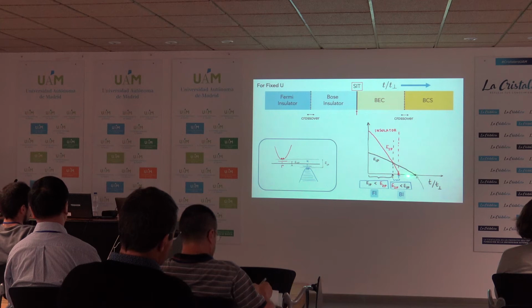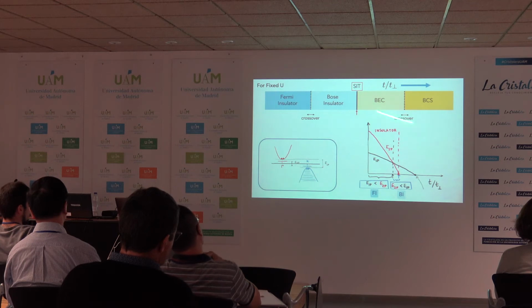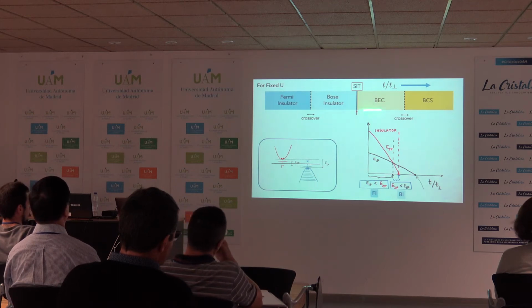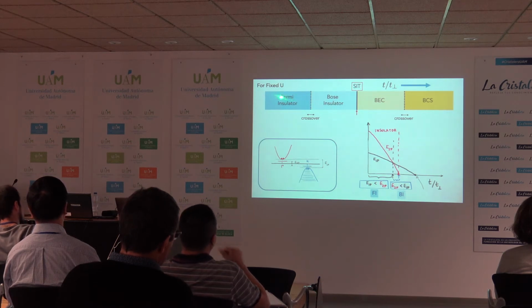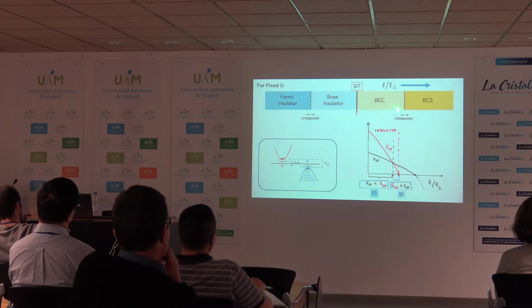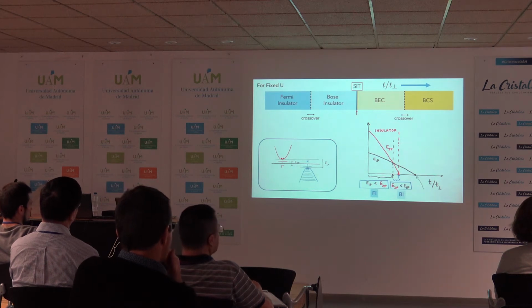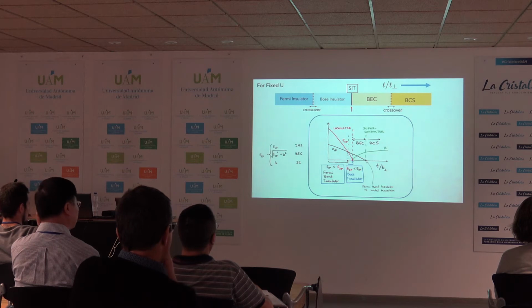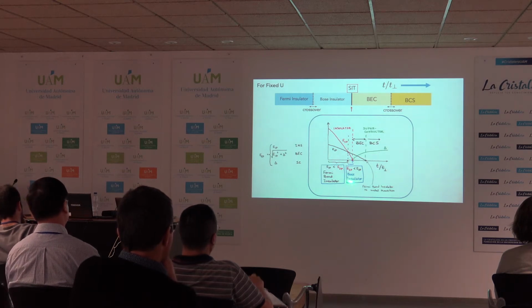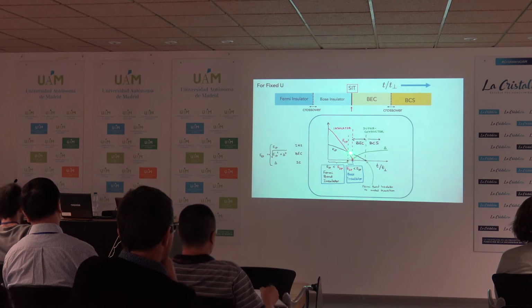So now at some point, this two-particle gap will go to zero, and that's where the insulator will enter a superconductor. So if there is a superconducting state lurking nearby, there is no way to go from just a single particle gap state directly to the superconductor. You will go through a bosonic state intervening. Okay, now in the superconductor side, again you see that, so what we find is that the single particle gap in fact remains finite throughout this insulator to superconducting transition.